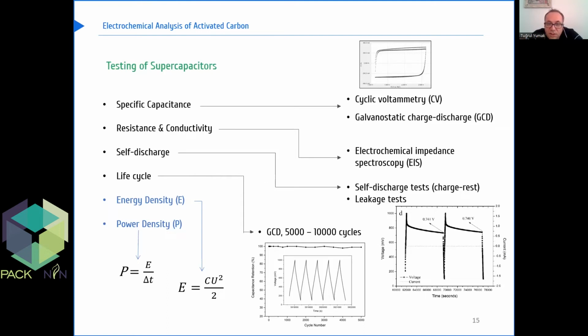In the GCD technique, the specific capacitance is calculated from the discharge curves after excluding the IR drop. However, the whole GCD curve gives the whole charge capacity and, most importantly, the Coulombic efficiency of the electrode material. In EDLCs, the symmetric triangular shape of the GCD curves proves the capacitive behavior is expected.